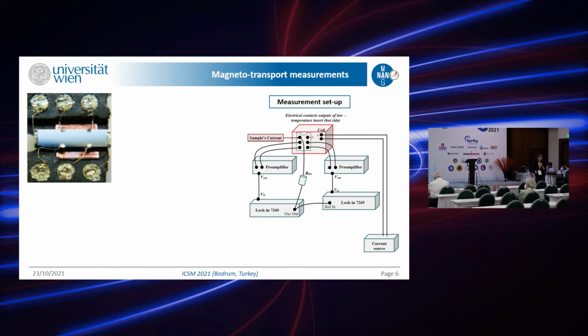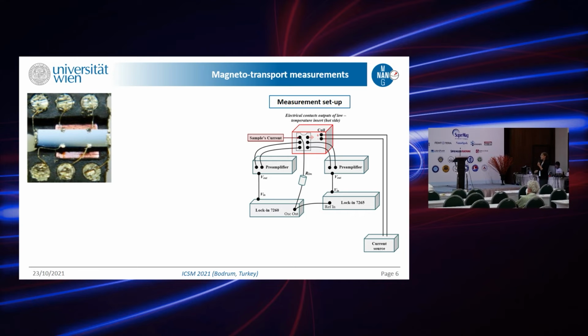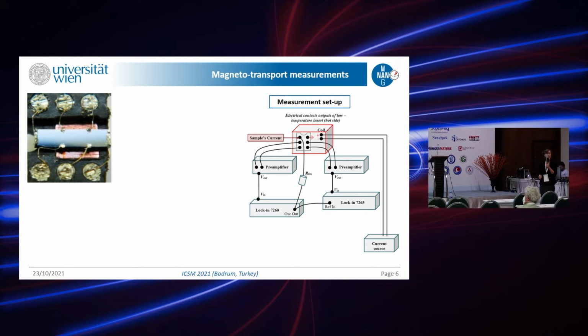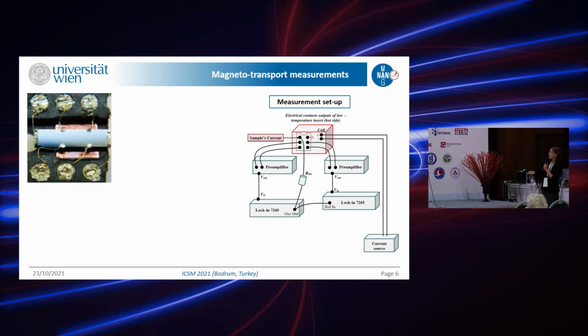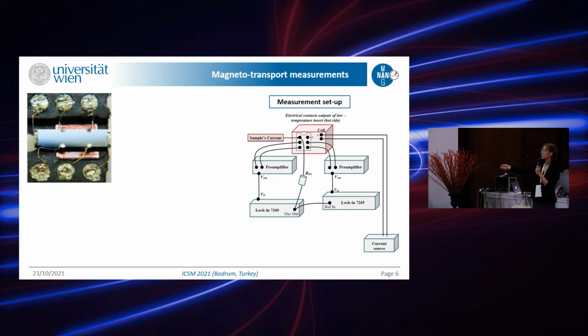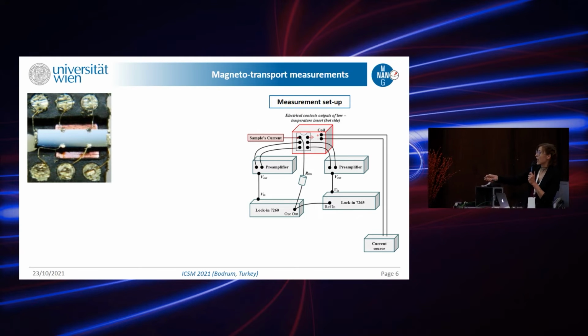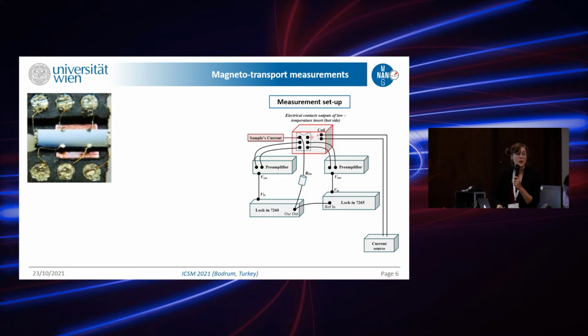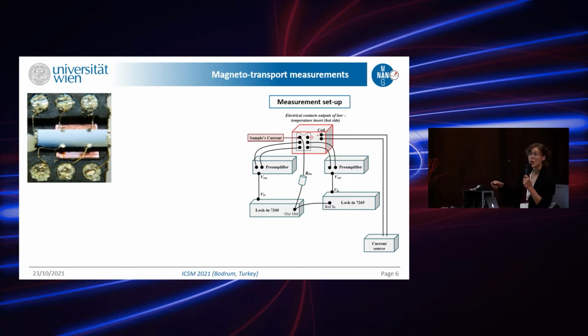So this is a typical view of our sample. We performed our measurements on Hall bar shaped samples, in a Hall bar configuration of the contacts. On this occasion we contacted them manually with indium, and the sample was put on a chip and connected with golden wires. Then we could put our chip inside the magnetic coil, which is connected to the contact output in the measurement setup, as you may see. And then we connect the corresponding contacts to lock-ins through preamplifiers and collect our signal.